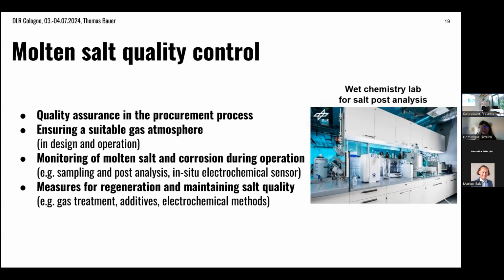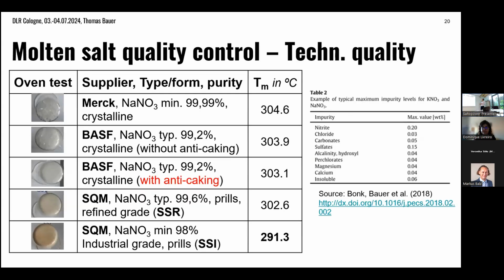Then there are also ways, but that's still under development, of regenerating salt and maintaining the salt quality once you see some decomposition. But I think we are still at a rather early stage in this. But there seem to be approaches and means to regenerate also solar salt once you see decomposition. To show some practical pictures, you see here sodium nitrate with different qualities, and you can see very nice crystals. And here you see already the impurities. Optically, that's 98% purity.